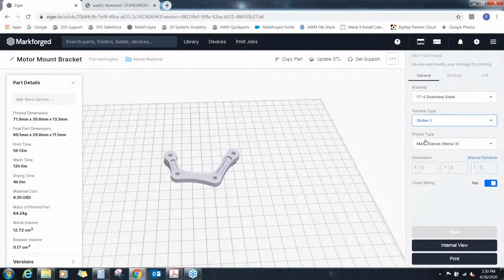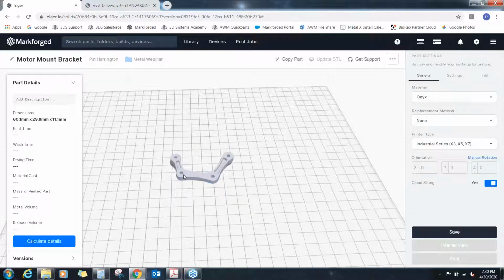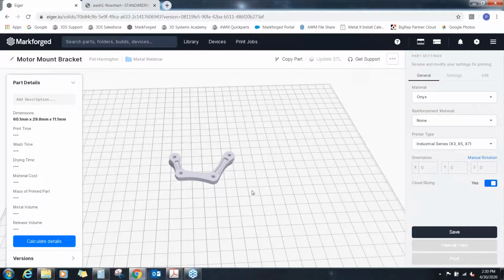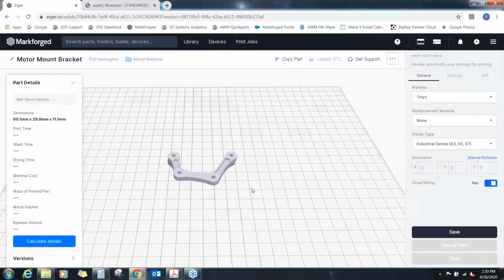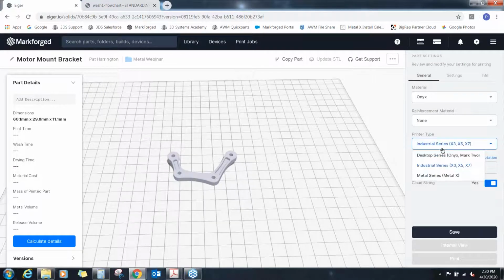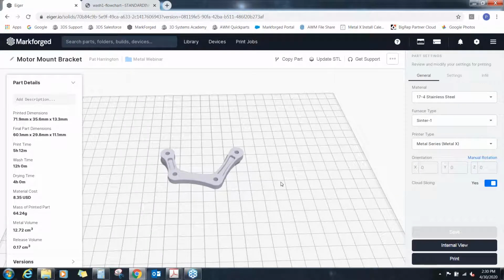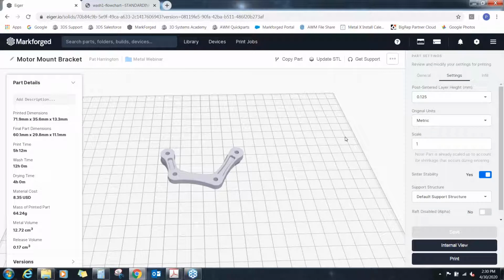So I'll show you the difference here. If I switch over to our composite machine, this is the true size of the part that will be your finished product after it's sent through the whole process. And then this scaled up version is the scale at which it will print to accommodate for that shrink factor. Okay, so 5 thou is the equivalent of 0.125 millimeters, and that will be your post-sintered layer height.